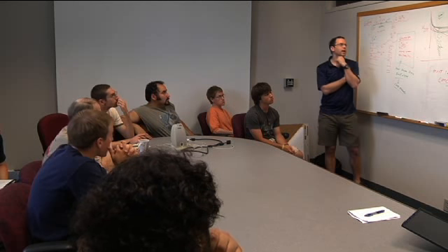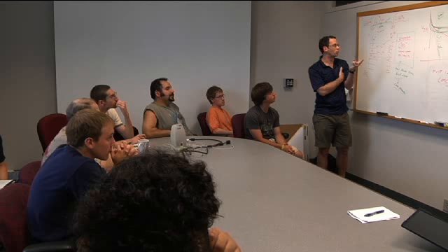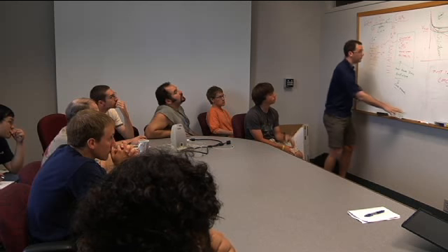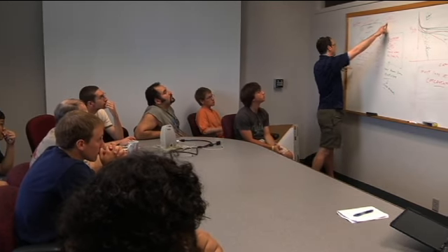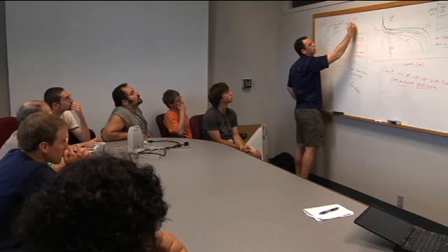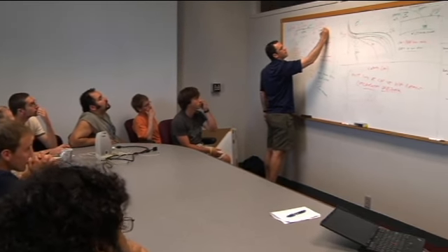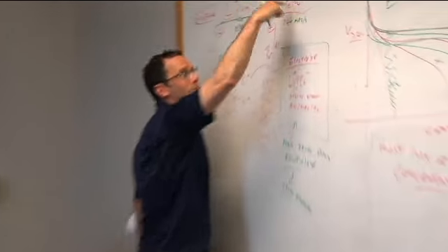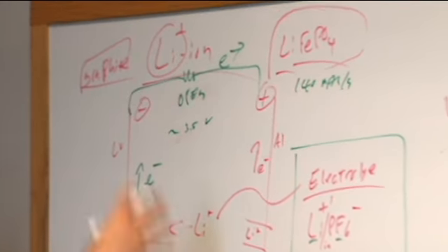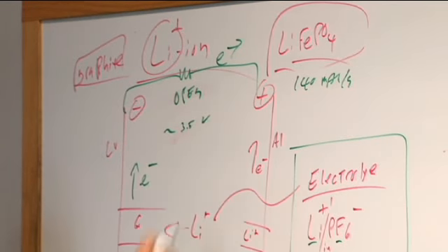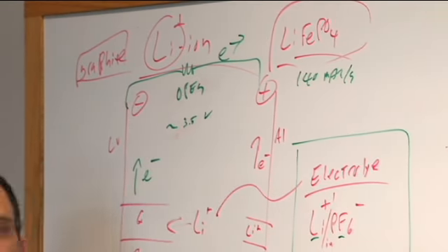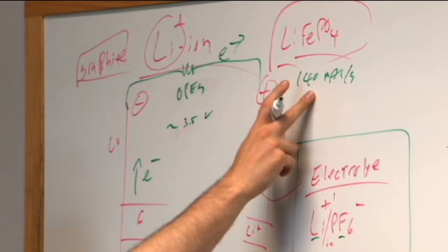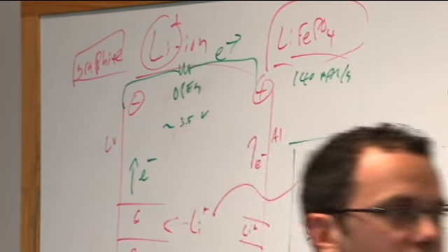Yeah, more or less. It's a function of two things. One is the absolute materials function, which is 140 milliamp hours per gram of this. So if I have something that's much higher here and I put it in the same structure, obviously it will increase. But for any given set of materials, it's the density and the thickness of this, and the overall size of the battery.